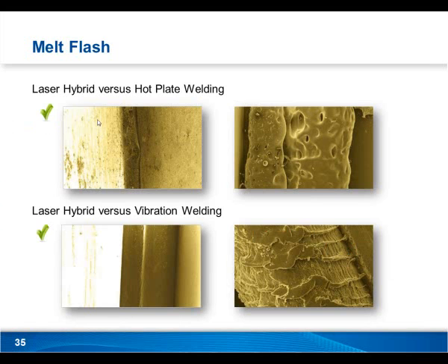So here's a comparison of laser hybrid versus hot plate on the top. You can see this is a zoomed in view of the joint. You can see a nice clean joint here with laser hybrid welding. And then as we move into hot plate, you can see that it's this inhomogeneous structure. A lot of melt blowout occurs with hot plate welding, and stringing. We've all seen the stringing happen, and so it leaves inconsistent joints. That's what I'm trying to get at. And then again on the bottom, nice clean joint with laser hybrid welding, and then vibration, you get this scaling effect. A lot of particulates involved with vibration welding.